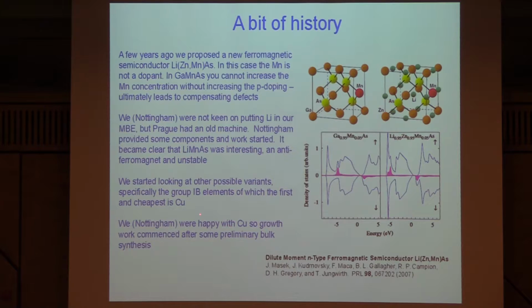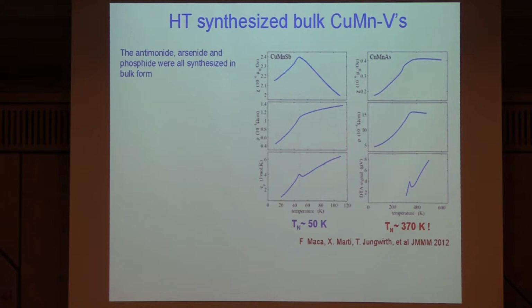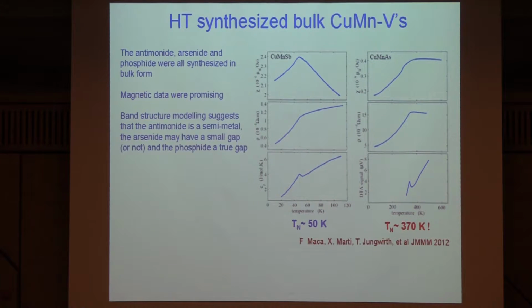Okay, and of course the cheapest is copper, so I've not got much money, so we put copper in the machine, and we thought, okay, while we're getting the machine ready to grow copper manganese arsenide, we'll obviously do some preliminary work, and we did some bulk growth, so we did some bulk synthesis. Okay, so high temperature synthesized copper manganese antimonide, arsenide, and phosphide were all done. And the magnetic data were extremely promising.